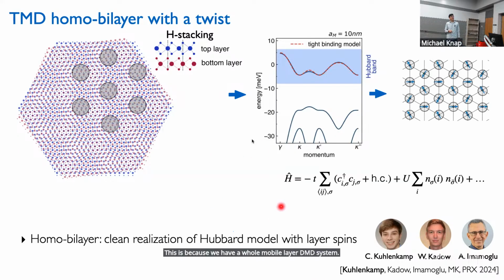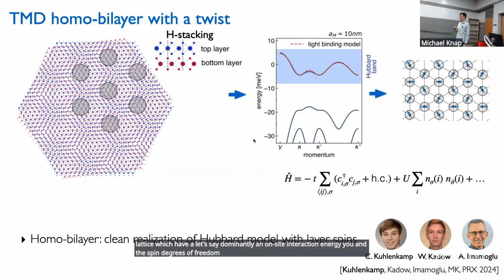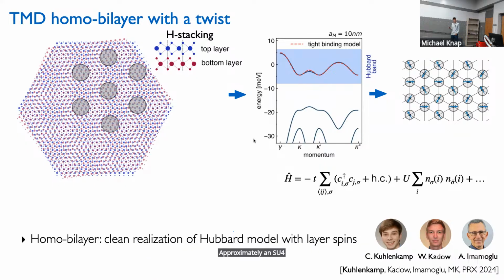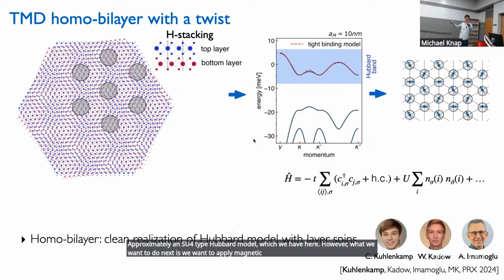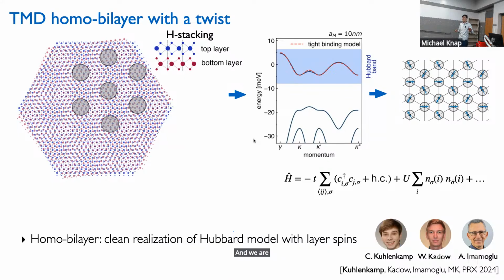So effectively, we get a Hubbard model of electrons hopping on a triangular lattice, which have, let's say, a dominant on-site interaction energy U, and the spin degrees of freedom are now top and bottom spins. We also have the electron spin degree of freedom. So this is actually approximately an SU(4) type Hubbard model. However, what we want to do next is apply magnetic fields perpendicular to the layer, which then drive a ferromagnetic transition in the electronic spin. So the electronic spin will be out of the game, and we are left with an SU(2) symmetric Hubbard model in the presence of a magnetic field. And that is a very interesting model. We will see step by step.